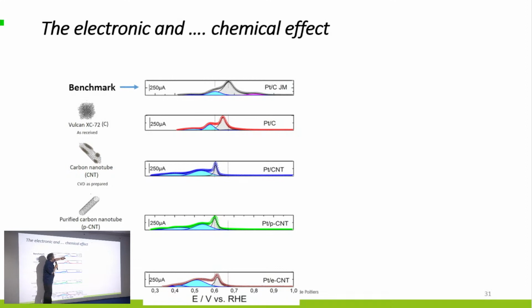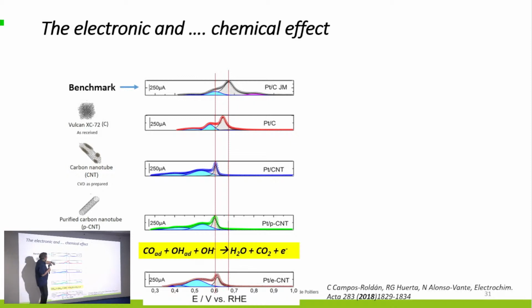Look, it appears here this kind of wave. That means the CO adsorbed on platinum is being affected by the surrounding medium, which is the sp2 region, which acts as an OH source, okay? And that helps the oxidation of CO to CO2. And that's what I call the chemical effect, but the electronic effect is there. Yes, you see that the main peak is also shifted towards negative potential.